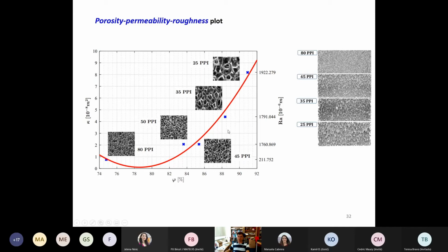And you can see that it has a sort of quadratic behavior. The main message here is that the higher the porosity, i.e. less material, the rougher it gets, which makes sense, and also the more permeable, easier for air to flow in. Is this good? Not so much. For aviation purposes, we don't want something with very large pores, because that means higher maintenance and more fragility. We prefer something that has very small pores, but with very high permeability. That's the holy grail of porous material for aerodynamic, aeroacoustic purposes that we're trying